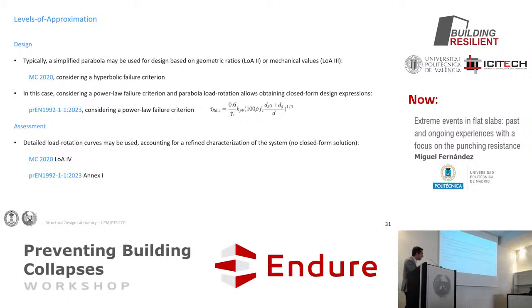And by the way, you see that here is D, and this is the power 1/3. So this is the size effect factor, if you want. And for assessment, it is opening the door to much more complex analysis. For instance, this full flat slab with redistribution between hogging and sagging regions and so on. And this is acquired in model code, for instance, model code level 4, but also in Annex I, which is informative, by the way, of the EN, so the future Eurocode as it is now.